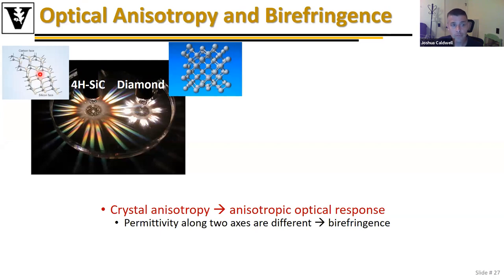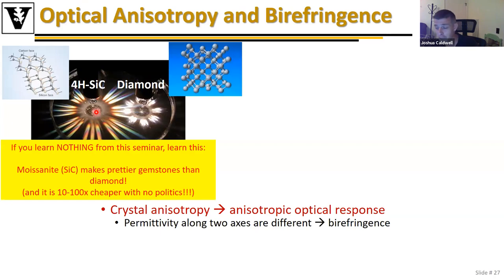However, due to the birefringence, or this crystal anisotropy, 4H silicon carbide actually gives this prismatic effect as it separates out the colors, due to the light traveling at different speeds and the dispersion in that permittivity. So if you learn nothing else from me today, especially where my screen will probably lock up again in a minute, just remember that moissanite, which is a silicon carbide gemstone, actually makes a prettier gemstone than diamond, about 10 to 100 times cheaper, and comes with none of the politics. So that's a good start.